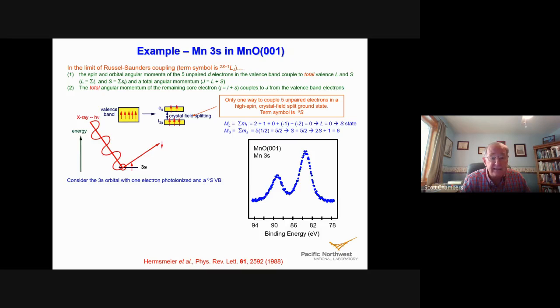Now let's think about coupling that sextet S for the valence band with the remaining 3s electron after photoemission. Well, we can either photoionize the spin up or the spin down electron in the 3s orbital, and the remaining electron then is going to have a J of 1/2, and the projection can be either 1/2 or minus 1/2, and that's going to couple with our sextet S, which is the 5 unpaired d electrons. Let's think then about the total orbital angular momentum of the whole system. It's going to be the remaining 3s electron plus the valence band. And since everything is S-like, then the sum is going to be S-like, so it's only going to be S states for the orbital angular momentum.